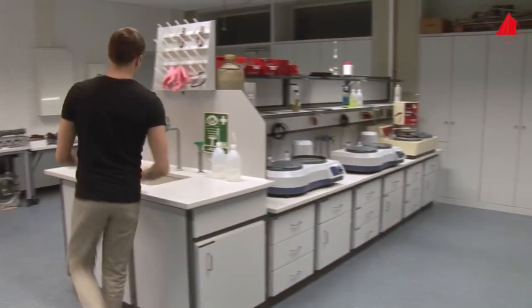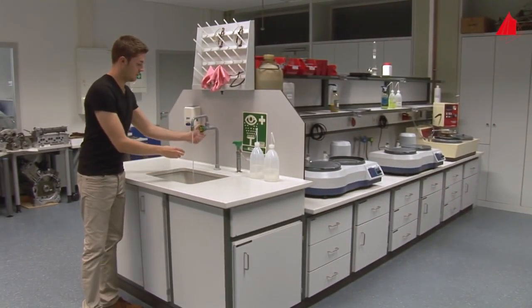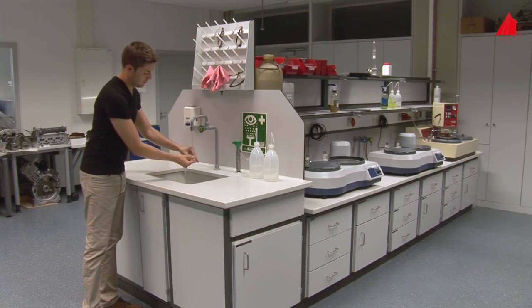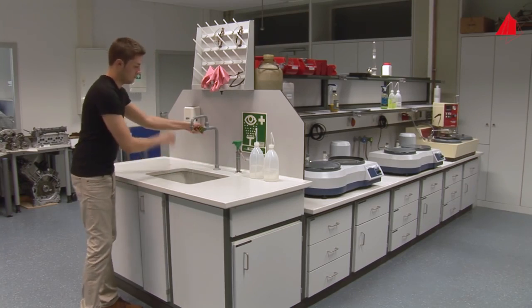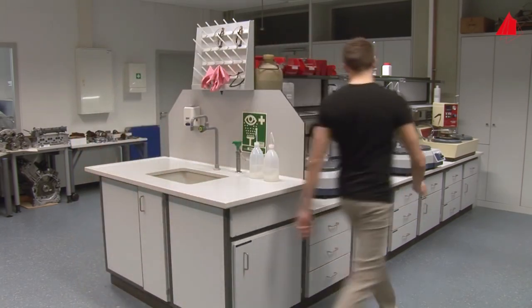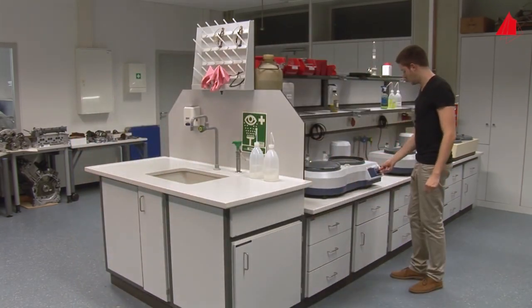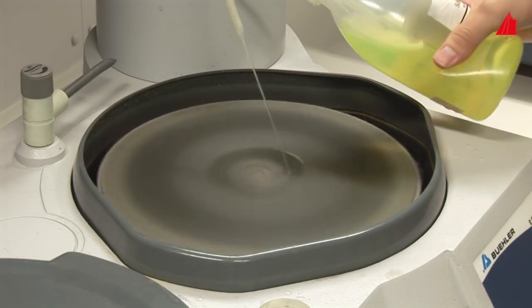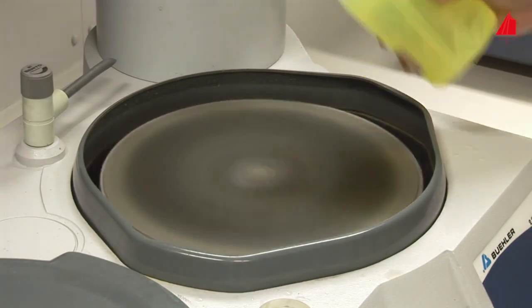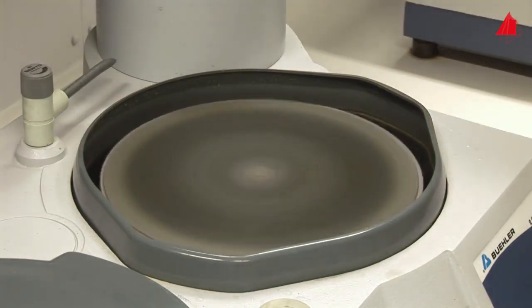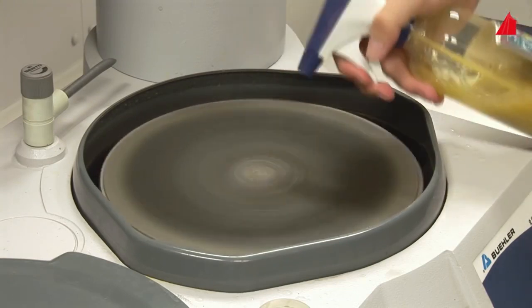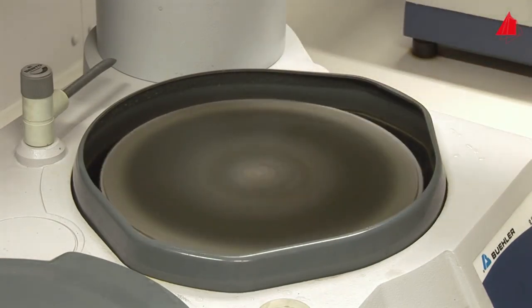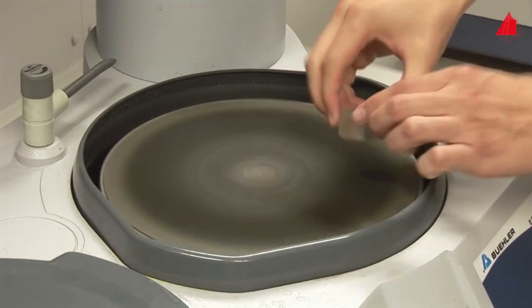Hands should be washed as well, so that no unwanted particles find their way to the sample and the polishing cloth. Now the material tester can start with a first polishing operation. He chooses a polishing disc equipped with hard cloth of low resilience, moistens the cloth with a suitable lubricant, and adds 2 splashes of diamond suspension of particle size 6 micrometers.